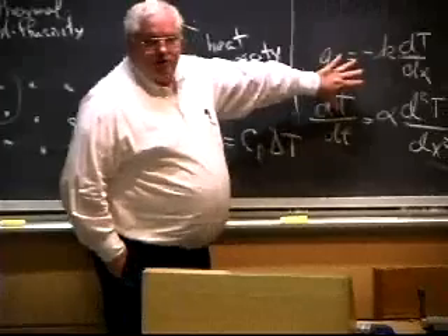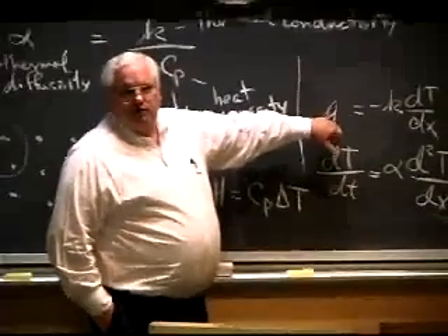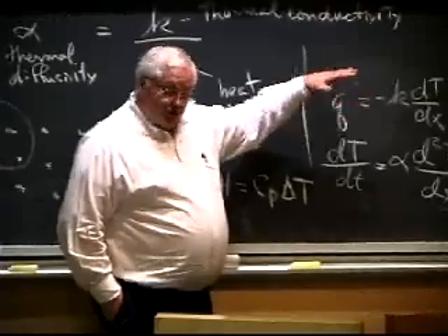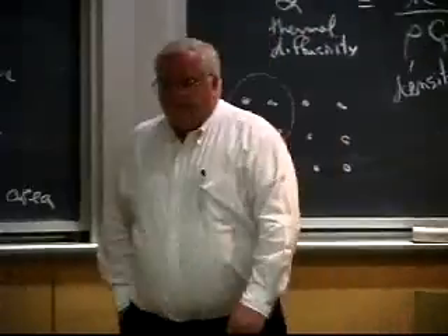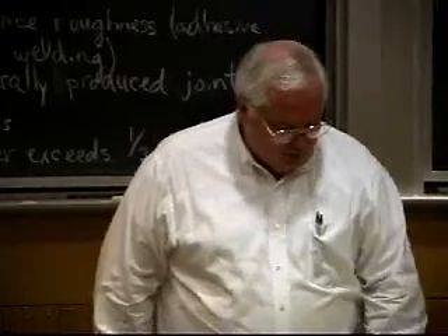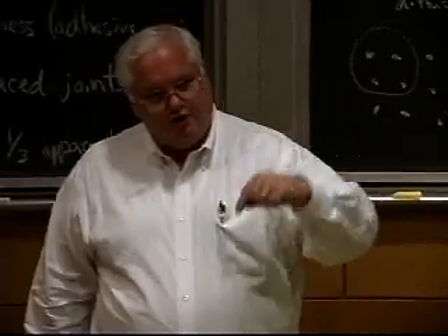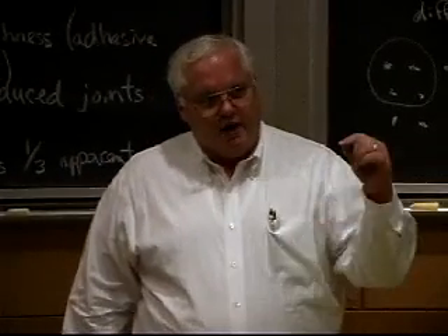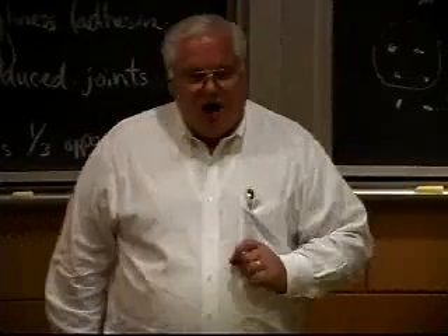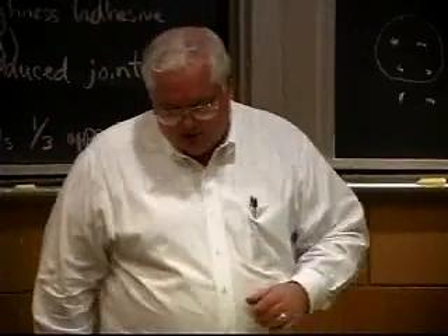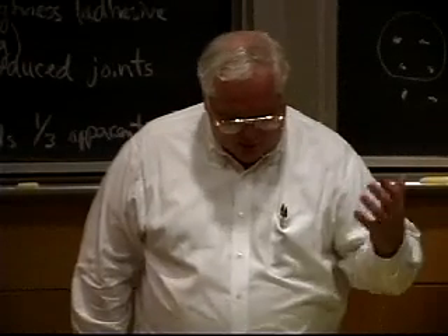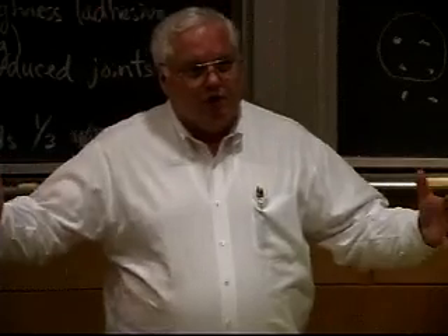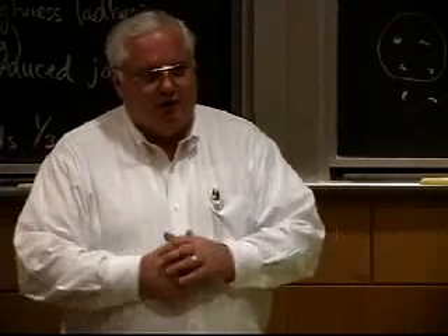And in fact, the advantage of the process we were working on was the reason most people can only lay down 5 or 10 pounds an hour is the thermal conductivity limitation. You got to suck the heat out of the part, and first you have to put it in, then you have to suck it out. But by using very high power electron beams, you actually can overcome some of those things because you don't have just surface heating. You actually can penetrate the heat down into the part, so you don't have to wait for the heat to diffuse it. You actually can deposit it several millimeters beneath the surface, and so you can put down metal much faster. However, you do have problems. You have to have 3-foot thick walls, concrete walls, because of the X-rays coming off this and little problems like that.